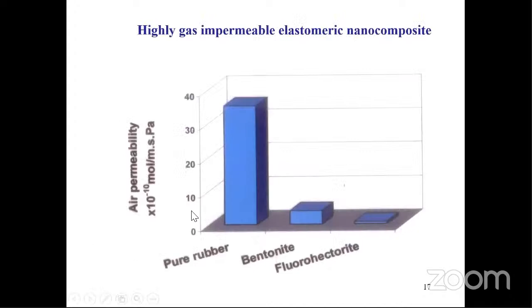See, look at the air permeability. Natural rubber has a very high level of air permeability. But you put 5% of bentonite or a fluorohectorite, and the permeability is dramatically decreased. Very dramatic reduction in permeability. I can show you how we organize the clay platelets. This is natural rubber. You see, we have organized the clay platelets beautifully.